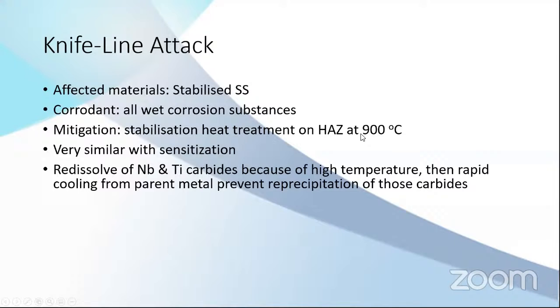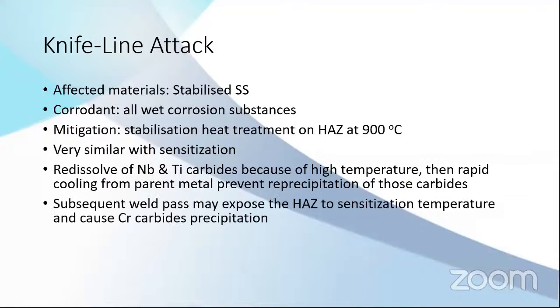And the problem with this is when the welding has quite high heat input, the niobium and titanium carbides dissolve again. So the carbides become free again. The carbon atoms become free again. And then it's cooled immediately because it's located in the HAZ. And because of the fast cooling, the niobium and titanium don't combine with the carbons. So there are no more niobium and titanium carbides in the HAZ area. So when the HAZ is exposed to the sensitization temperature, 450 to 870, it reacts with the chromium and it causes sensitization.